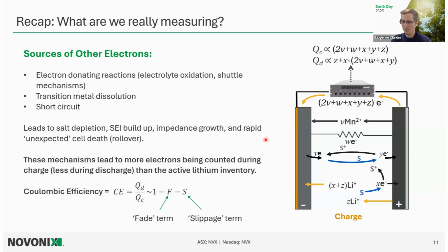So I'll walk through a couple of these and then talk about what that means for our Coulomb counting. So for the top mechanism here, we're looking at manganese dissolution. So especially in cell chemistries like LMFP, manganese dissolution is a really big topic. And when this happens, to create charge balance within the cell, we actually have to count 2 electrons through this external circuit in order to maintain this charge balance. And so as we're charging our cell, removing lithium from the cathode, we're counting those electrons, but we're also causing electrons to do some of these other mechanisms.